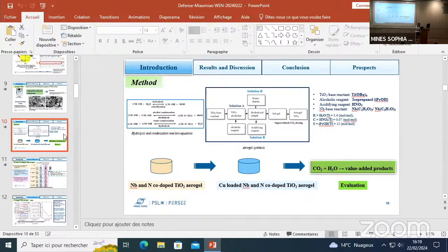because when we burn in air, you make the degradation into CO2. But if we don't have enough air, sometimes, maybe on N2 also, when we make the calcination, probably you can see some residual carbon atoms at the surface. So maybe it could be due to the residual groups.